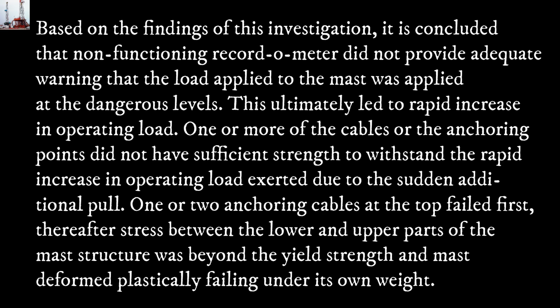One or more of the cables or the anchoring points did not have sufficient strength to withstand the rapid increase in operating load exerted due to the sudden additional pull. One or two anchoring cables at the top failed first. Thereafter, stress between the lower and upper parts of the mast structure was beyond the yield strength and the mast deformed plastically, failing under its own weight.